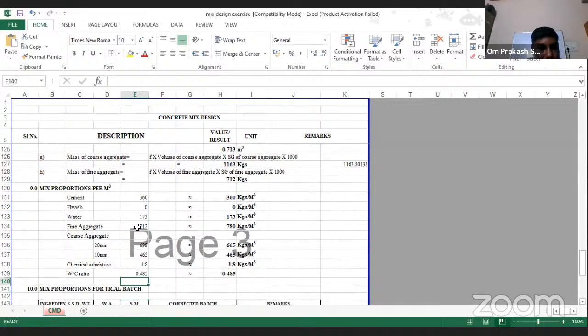So here is our final proportion. What is it? Cement is 360, water is 173, fine aggregate is 712, 20 mm is 665, 10 mm is 465. Chemical admixture I have taken as 0.5% of cement content, so it is 1.8 kg, and the water cement ratio is 0.485.